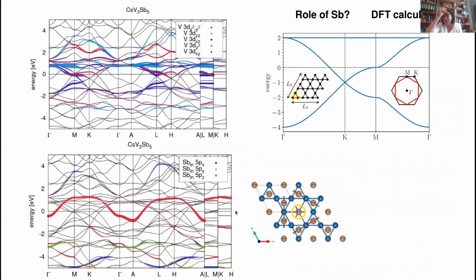What I didn't talk about is, going to a more realistic description, taking the whole system. I'm showing here the band structure of the whole system. You have vanadium bands, but also antimony bands. And the antimony bands, as you can see, are in fact at the Fermi level all over. So antimony is the elephant in the room.